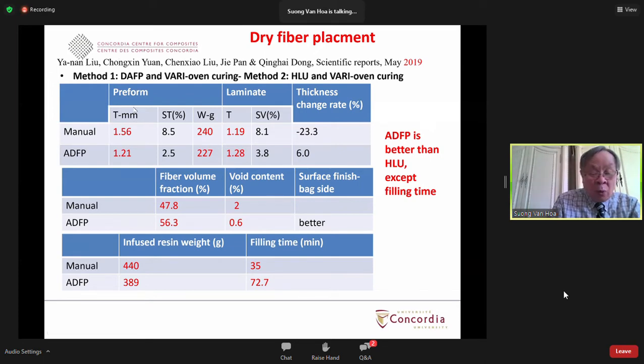So when they make the preform, they found that the preform made by AFP is thinner, 1.56 to 1.21. It weighs less than the case of the hand layup, but when you make the laminate, then the laminate becomes thicker. The reason for that is because during the laminate fabrication, people apply pressure, and the pressure has more effect on the preform than the case of the AFP. The fiber volume fraction in the case of AFP is larger, less void, and also you use less resin. So these are all advantages of the automated fiber placement for dry preform, except for the filling time. When you are filling the resin into the composite, then it takes longer, more than 2 times the time required in order to fill.